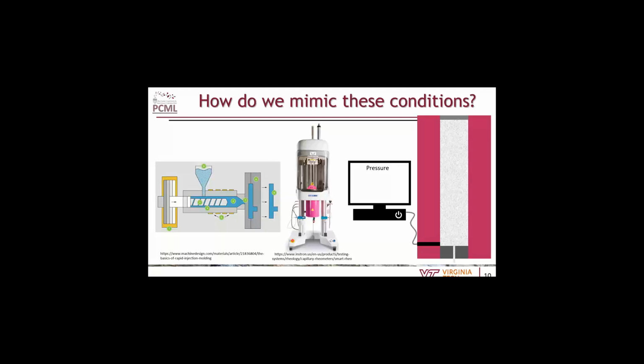What happens is you've got this barrel that you fill with material. At the bottom of the barrel is your die that you put in, where you can restrict your contraction. We tend to use a 1 millimeter die because they're easy, and that's what we have. Then you have a pressure sensor right above that, so you can use the pressure drop from the pressure sensor above the die to the plain regular atmospheric pressure outside the die, and use those 2 points to calculate how much energy is lost as your material travels through the capillary.